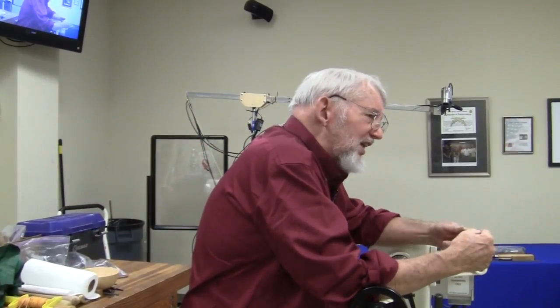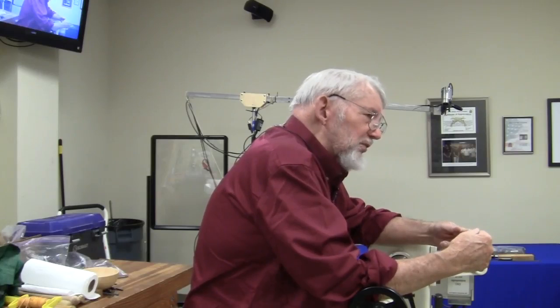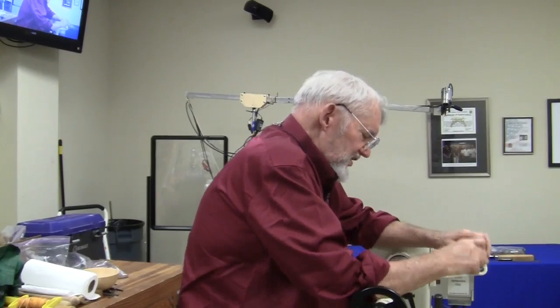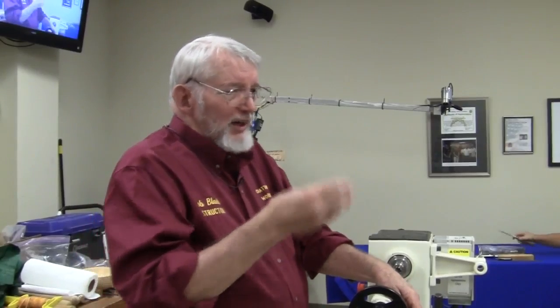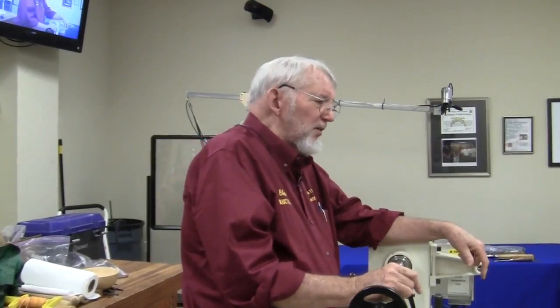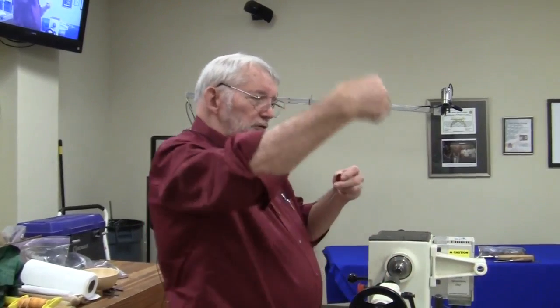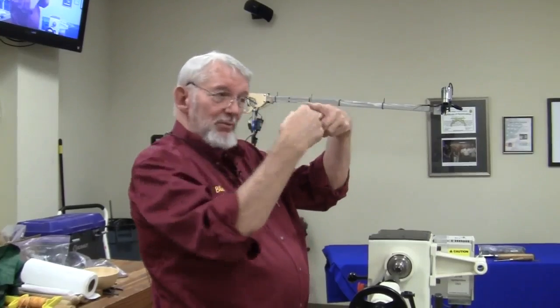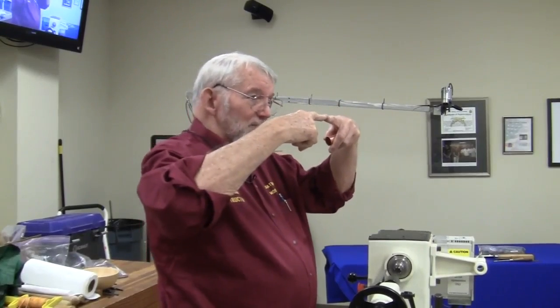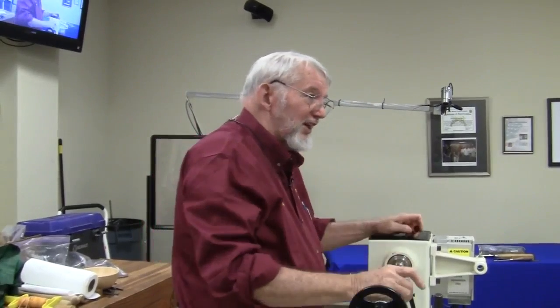When I'm doing it, I'm looking for the steel to go red, not really bright. And you just touch the solder, and we'll talk about it a little more later on if we have time, fit is everything. I've got an old Powermatic Model 30 belt disc grinder with the 12-inch disc, and I use that to get my ends square. Get them together with a light behind them, and when you've got the lights out before you put flux on it, you're fit.